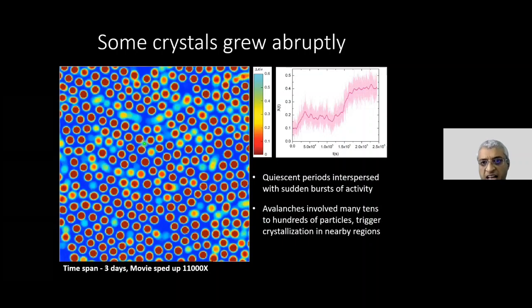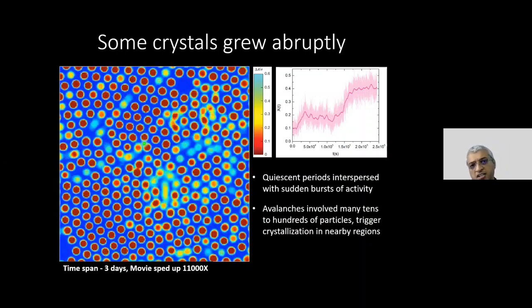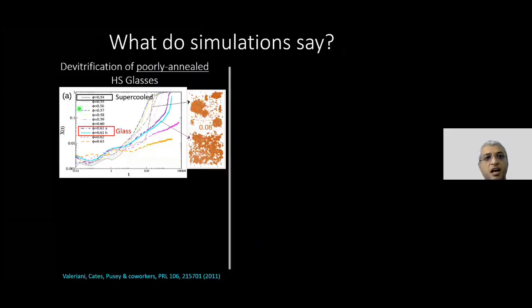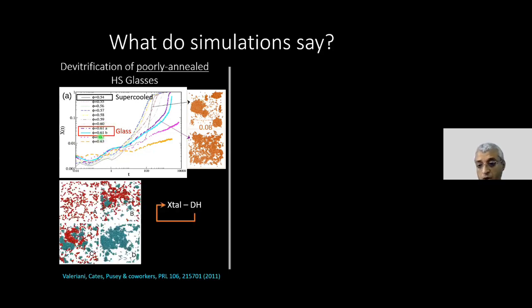Now, before we started these experiments, of course, we were guided by some simulation studies, and we'll try to map what we see onto what's known from simulations. So there were two sets of simulations done, and let me first show you the first one. This was work that came out about 10 years ago. And what I'm once again plotting for you is x of t as a function of time. If you have a supercooled liquid, of course you get compact crystals because you are at a low enough volume fraction. But if you are in the glass, the x of t profile that they see basically increases steadily. Okay, this was for a poorly annealed glass, and the crystal shapes are not compact. I am showing you this for a volume fraction of 0.61 in the simulations. Just like what we saw in the first route, there are these small clusters of activity and they trigger crystallization nearby. Okay, so that's what they found.